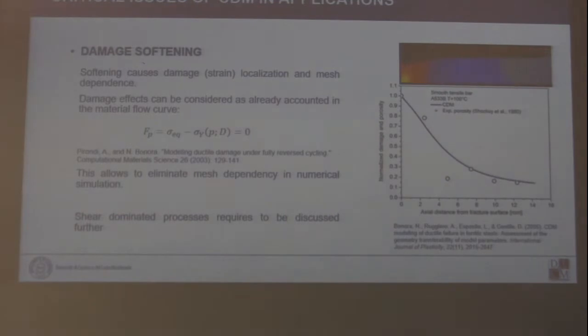And so we can get rid of the softening. If you can get rid of the softening, your life is much easier because your computational analysis becomes no longer mesh dependent. So the method is robust, and then you can use it in practical applications.